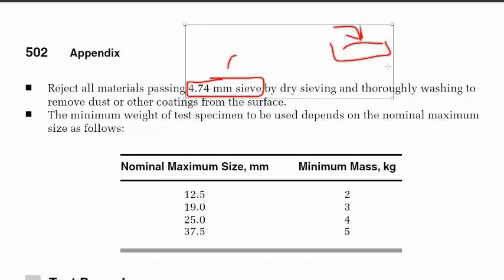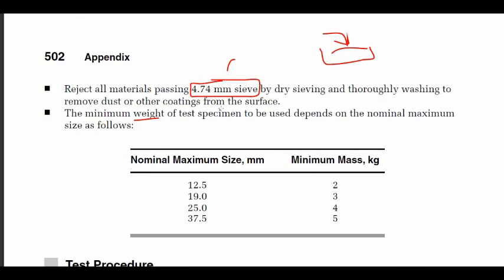So we need only this. This is part 2 of our experiment. First of all, you are going to see that we're going to reject all the material passing through this 4.7 millimeter sieve by dry sieving and thoroughly washing to remove the dust or other coatings from the surface. And then the minimum weight of the test specimen to be used depends on the nominal maximum size as follows. So we are going to have a relation between the maximum size of the aggregate, you need to check it, and the corresponding minimum mass of the sample that you're going to use.